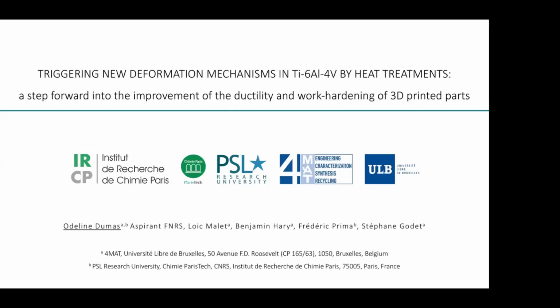What could be interesting is to try to have the finest microstructure possible, because when you have very tiny martensites, you improve your chance to have one self-accommodating group in one parent beta grain. When you change the size of the parent beta grain, you will have not one but several self-accommodating groups, and between them they cannot induce reorientation. So it will be better if you have just one. So maybe we can adjust the process on that point, but I think that's it.